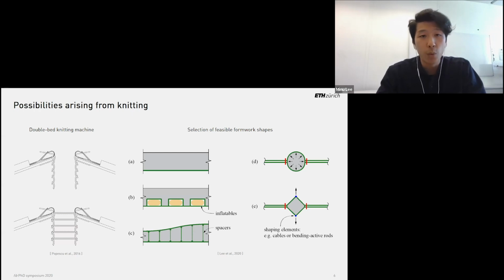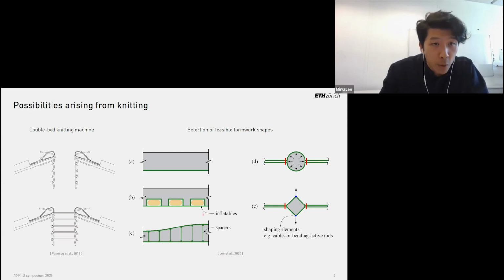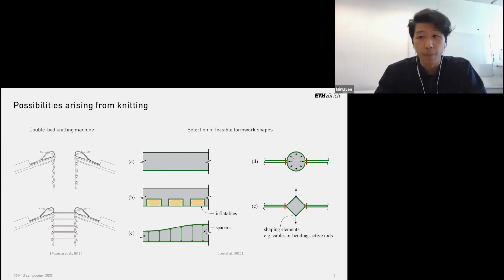Normally, the formwork would serve as a support bottom layer, as depicted in this picture here, where it's just on the bottom. In the KnitCandela pavilion, for instance, pockets were implemented and then inflated with balloons, which are these yellow bubbles, to create a ribbed cross-section that significantly saved weight and therefore gray energy.